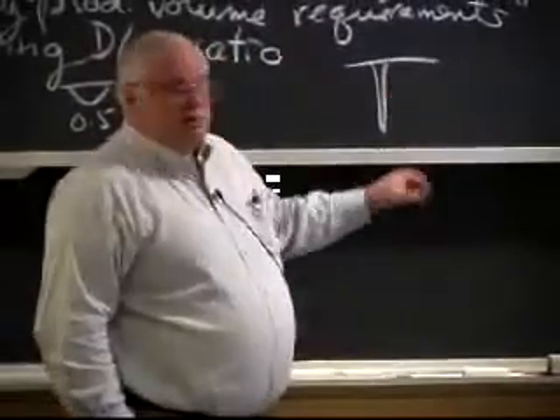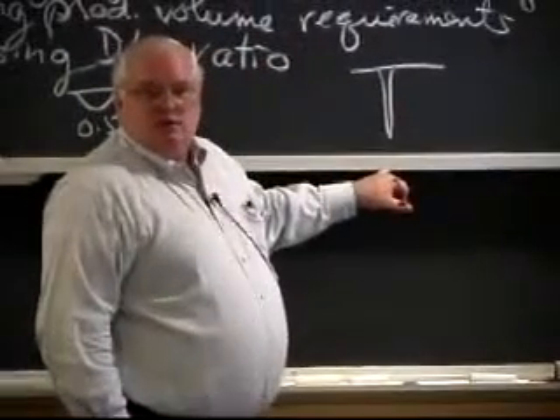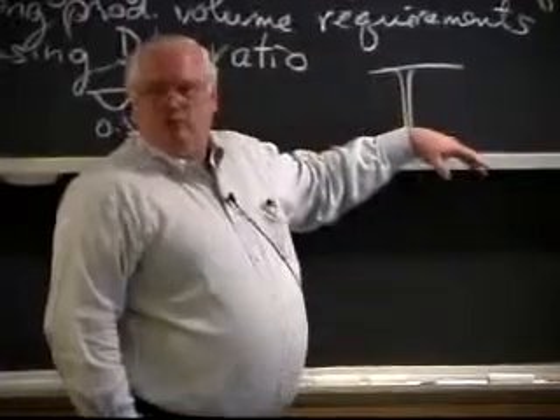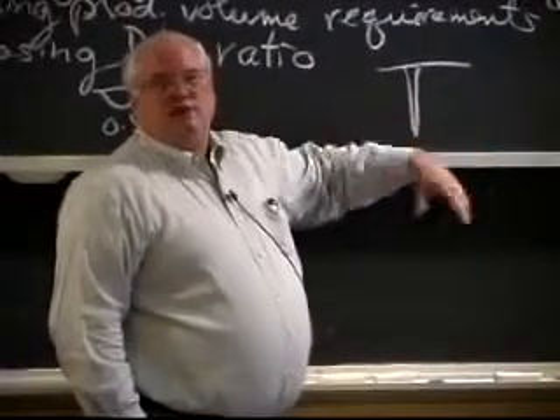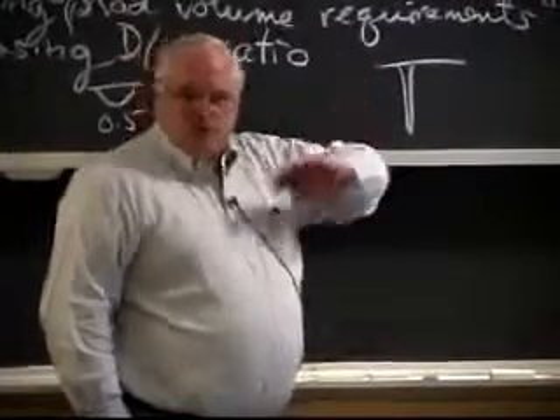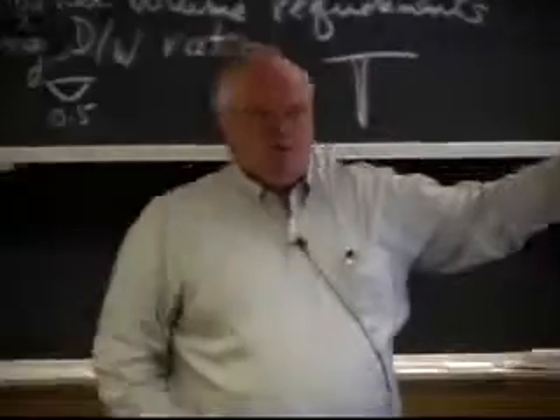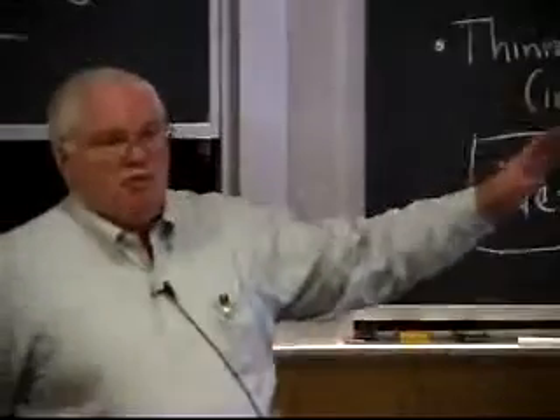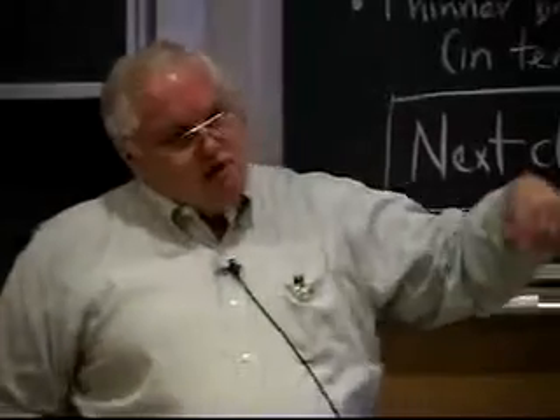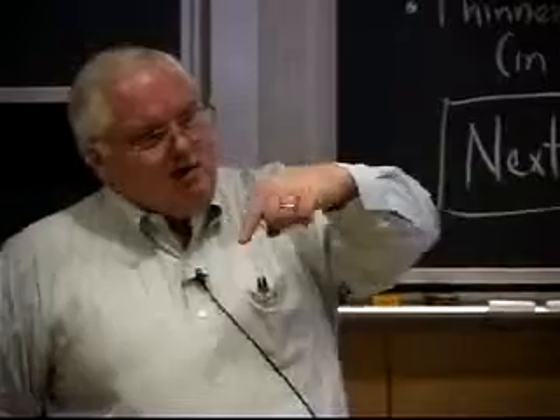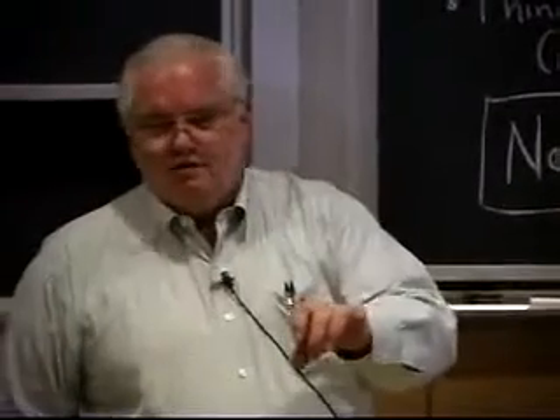At 10 to the seventh, I'm drilling holes. Well, at 10 to the sixth, you're drilling holes, but you're backfilling with liquid. At 10 to the seventh, you're drilling holes and you're blowing the liquid out or vaporizing it, and it doesn't exist anymore. But at 10 to the sixth, you drill a deep penetrating hole and the liquid flows around and fills in the hole behind, and that's how you get your penetration. And you saw that in the What Happens in High Energy Density movie, right?